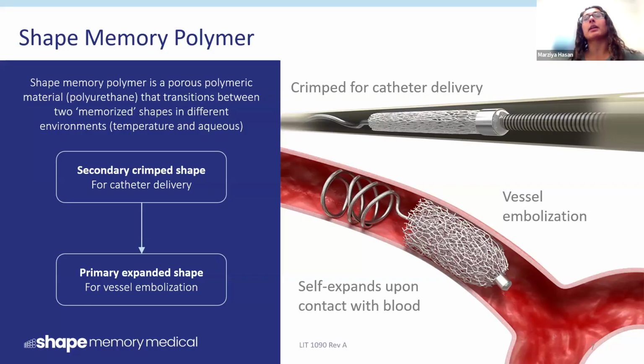So we've actually done experiments where we have taken foam cylinders, crimped foam cylindrical rods, and dropped them in cold water. And they'll stay like that for hours, like nothing will happen. The material will get plasticized, but it needs that heat stimulus to expand. So once it's moisture plasticized and it's in an elevated 37°C temperature, that's what causes the material to open up and self-expand. Okay, so it's body temperature.